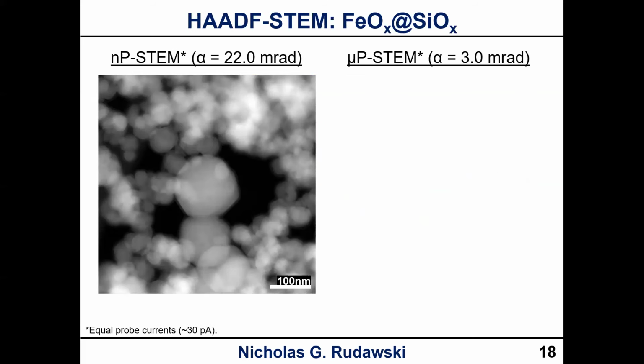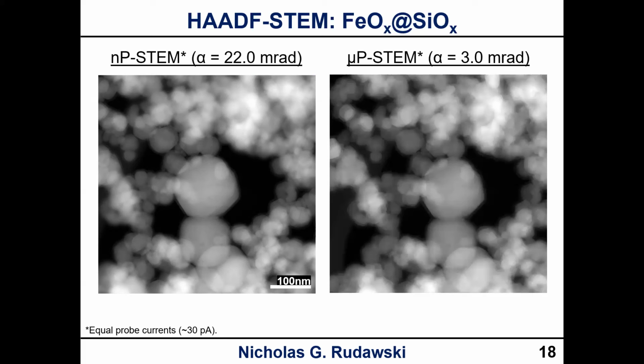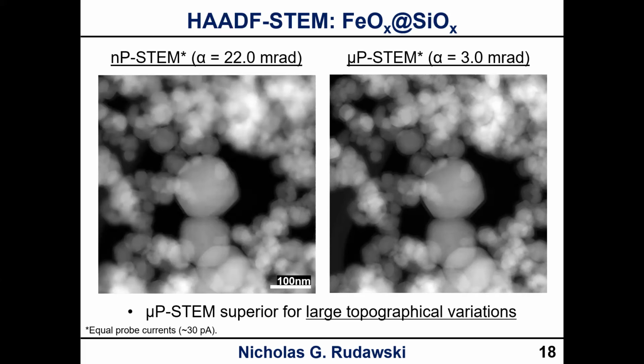Now if we look at a situation where we have a lot of topographical variation, again with the same two configurations we saw before, these are iron oxide nanoparticles with a silica coating. You can see in the nanoprobe image that parts of the image are not in focus. I optimized the focus for the middle, but in some of the areas around the edges it's getting blurry, because your depth of field is not very large. If we look at the same ROI in microprobe mode, we don't have that problem anymore. The entire field of view is now in focus, so we have a really large advantage when dealing with topographical variations.